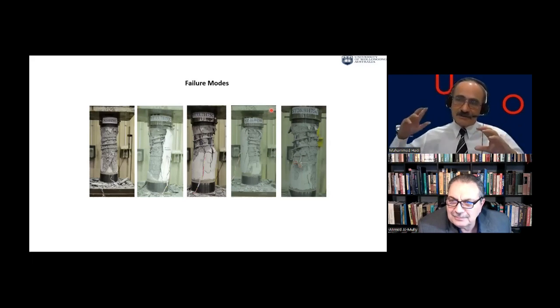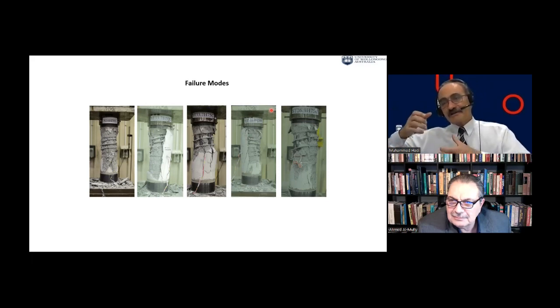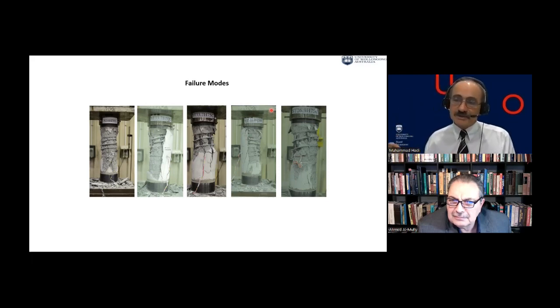So this is the failure. Now, we had a problem, and I will tell you about the problem. Bond. There was failure in the bond. So what we did, we had to dig the concrete and add washers and weld them. And then add concrete, wrap with FRP and test. So now it is in my database. Bond is important.